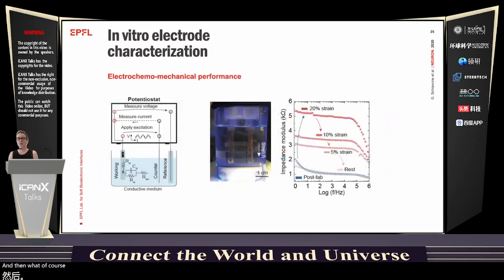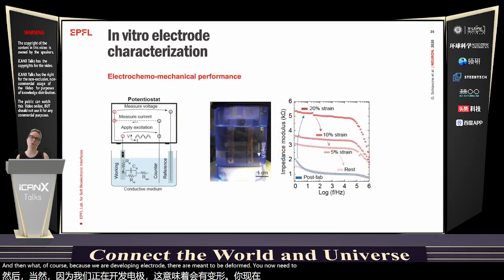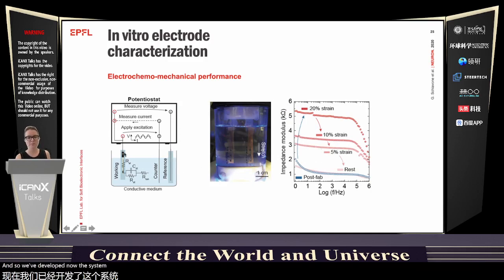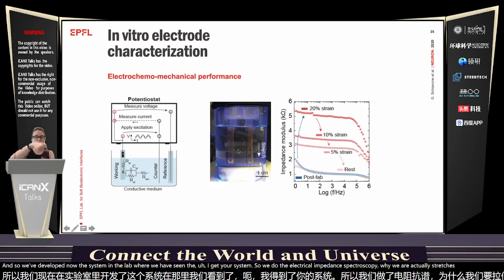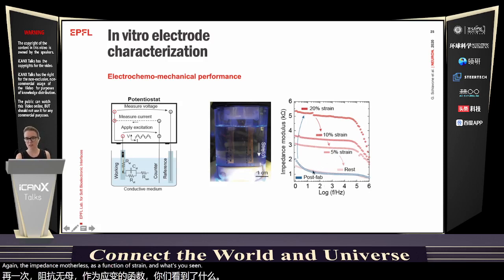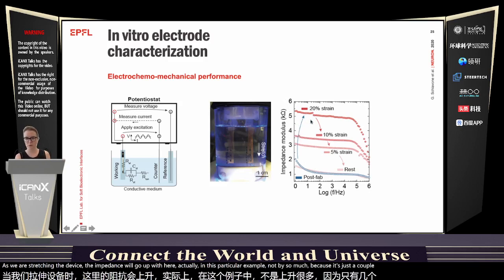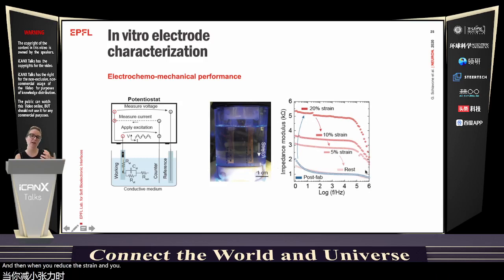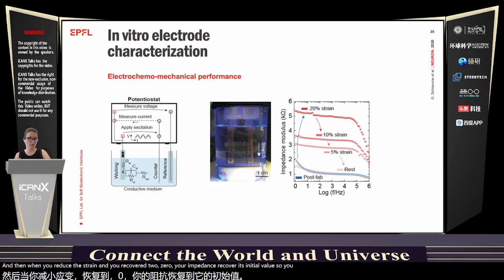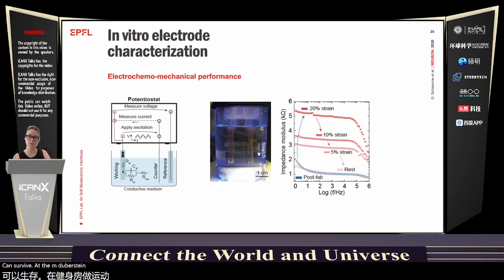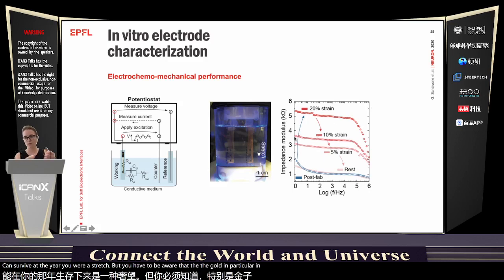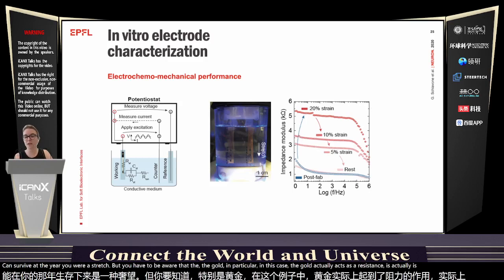And then, of course, because we are developing electrodes that are meant to be deformed, you now need to combine this electrochemical performance with mechanical deformation. And so we've developed this system in the lab where we have the EIS system. So we do the electrochemical impedance spectroscopy while we're actually stretching the device in a liquid. And then you can record the impedance modulus as a function of strain. What you see in this experiment is that as we're stretching the device, the impedance goes up. But in this particular sample, not by so much, because it's just a couple of kiloohms difference. And then when you reduce the strain and recover to zero, your impedance recovers its initial value. So you have a structure that can survive the overall stretch, but you have to be aware that the gold resistance is actually changing with applied strain.